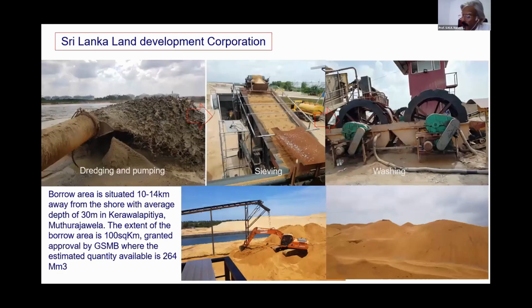Now, Sri Lanka Land Development Corporation is doing this job. They are dredging and pumping to a site in Muthurajawela, and they do sieving and washing, and this is the washed offshore sand. The borrow area is situated about 10 to 14 kilometers away from the shoreline with an average depth of 30 meters in Kerawalapitiya, Muthurajawela. The extent of the borrow area is about 100 square kilometers, and they got the approval from GSMB, where the estimated quantity available there is about 264 million cubic meters.